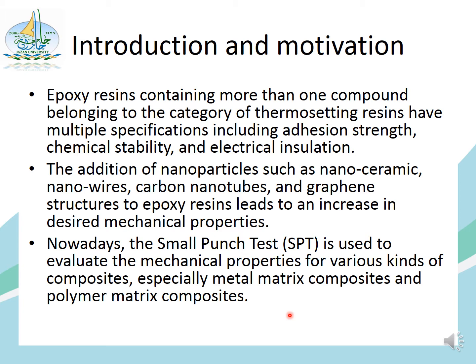However, nowadays the small punch test is used to evaluate the mechanical properties of various kinds of composites, especially metal matrix composites and also polymer matrix composites. So, the small punch test is a technique used to evaluate the mechanical behavior of a miniaturized thin disk. Also, the use of the small punch test has emerged as a potentially useful technique for mechanical characterization using small specimens. Therefore, one of the main objectives of the present work is to ensure the accuracy of the results obtained by the small punch test and compare them with the results obtained from the diametral tensile testing.